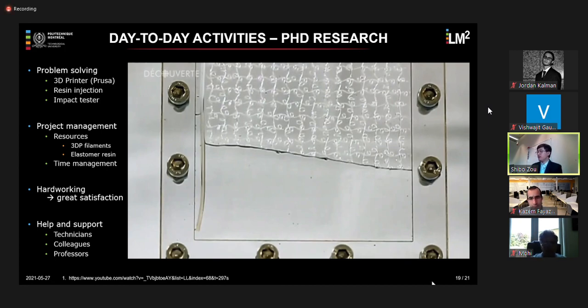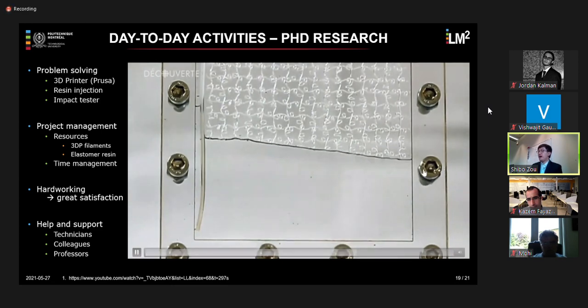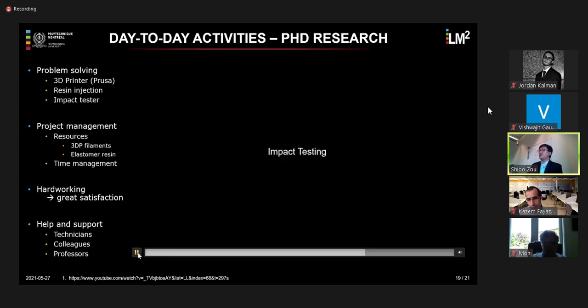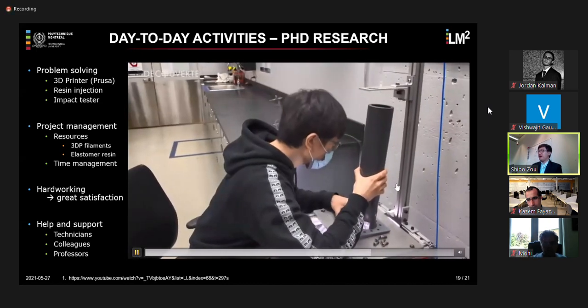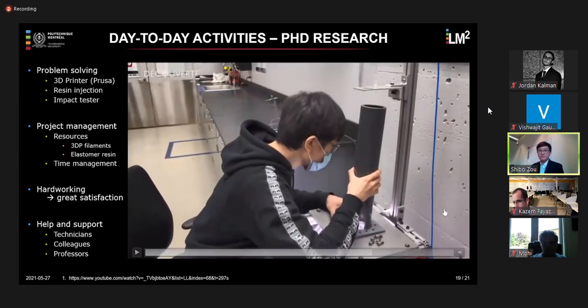And of course, last I'm going to show you the impact tester that we have in our lab. And also the story behind this impact tester: the material that we developed, according to my calculation, has an impact force that should be below 200 Newton. But the only available impact testing machine in our department has a load cell of above 10,000 Newton. So it's way higher than my composite could produce, and I couldn't use that impact tester.